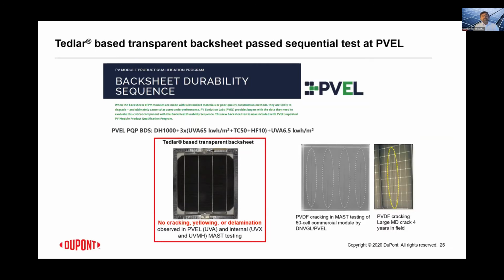And the transparent Tedlar-based backsheet has been taken through this sequential test in mini modules as well as full-size modules, and it has passed this pretty easily. We haven't seen any yellowing, delamination, or cracking, the things that we do look for. Case in point is that this test actually is very effective in catching the issues that I was showing earlier from the field in some materials like polyamide or PVDF. It has been able to rightfully simulate and predict cracking of PVDF and polyamide-based backsheet. I'm showing examples over here.